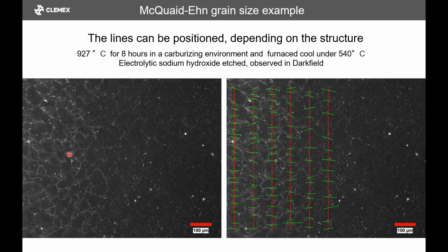Sometimes some material will react to bright field, but in this case, it is better with dark field. What we're doing here is just drawing lines that are representative of our surface. A circle will not be the right approach here, because you won't have any grains in parts of it, and you will end up with very long segments, which will throw off your values. Here, you can cover the number of lines, and we have about 4,000 microns of lines. Then we count the intercepts, and we have an accurate grain size measurement for a challenging structure.